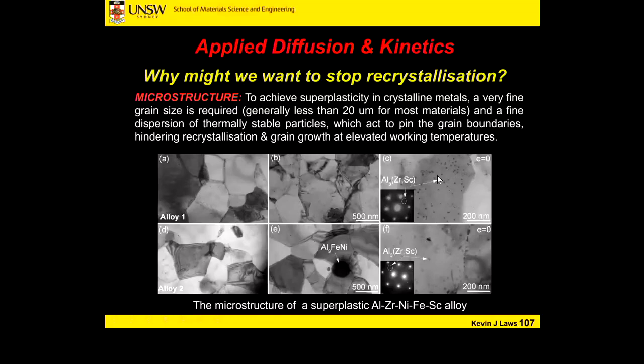What happens when we add those elements to our alloy? They produce a precipitate particle, typically something like an aluminium-3 zirconium or an aluminium-3 scandium particle. Tiny little particle. What those particles do is sit on the grain boundaries of our ultra-fine grain material, and they stop the grains from actually growing. So recrystallization during deformation isn't happening, partly because we've engineered these really fine particles sitting on grain boundaries, stopping recrystallized grains and existing grains from growing.